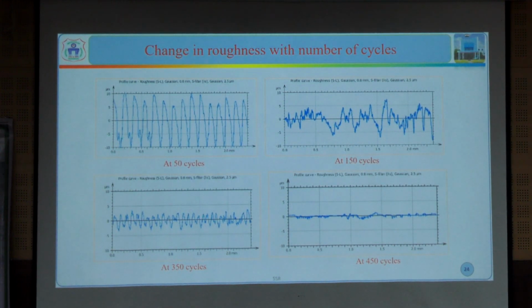So these are some of the results at different cycles: 50 cycles, 150 cycles, 350 cycles, 450 cycles. As I said, one cycle is when we pump with a to and fro action. Here we observe that at 450 cycles we are getting a certain finish. Let us say the Ra value from 1 micron, as per the scale here. The maximum peak here is some 10 micron, and here you can see some 0.1, 0.2. But this is not sufficient, and we also observe that it is taking more time. 450 cycles is huge, so we need to spend a lot of time for finishing.